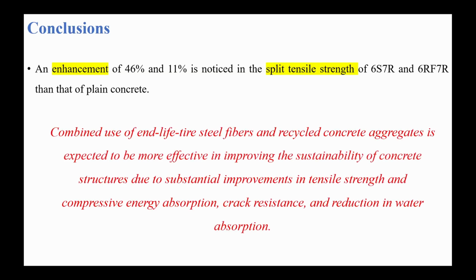So it can be concluded that the combined use of end-of-life steel fibers and recycled concrete aggregate is expected to be more effective in improving the sustainability of concrete structures due to substantial improvement in tensile strength and compressive energy absorption, and crack resistance and reduction in water absorption.